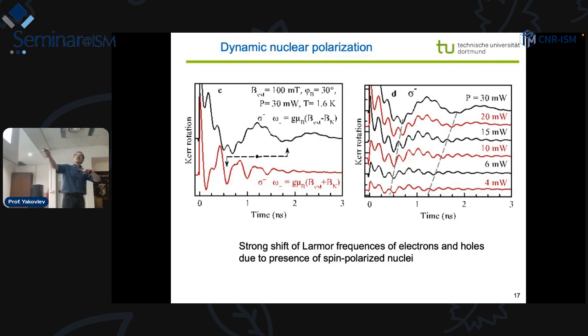And if we use sigma minus orientation, then the nuclear field Bn is subtracted from the external field. So the period of precession becomes larger. If we use sigma plus polarization, so it should be sigma plus here, I don't know, it's somehow missing, then the nuclear magnetic field is added to the external field, and the precession becomes faster. And the difference between these precessions depends on the power of excitation, because the more power we pump, the more the nuclear system will polarize, the more effective nuclear field appears.